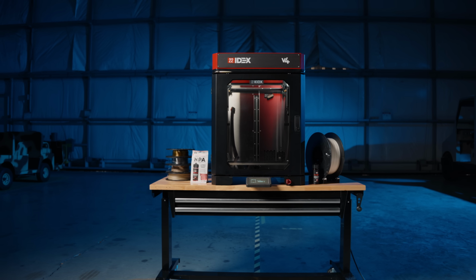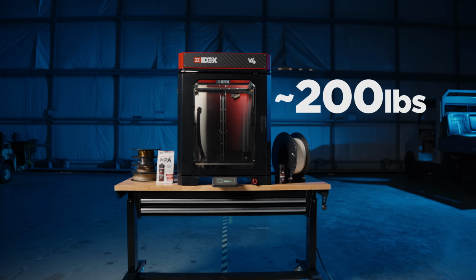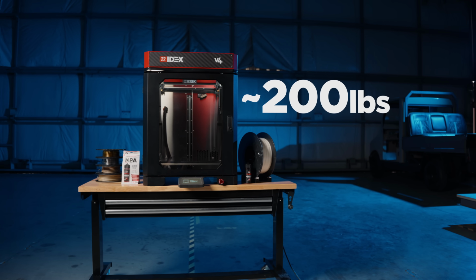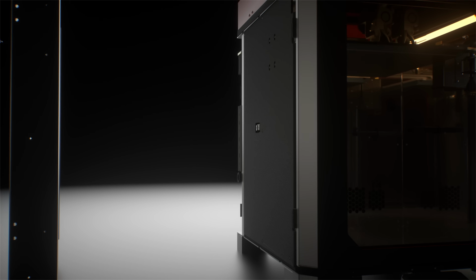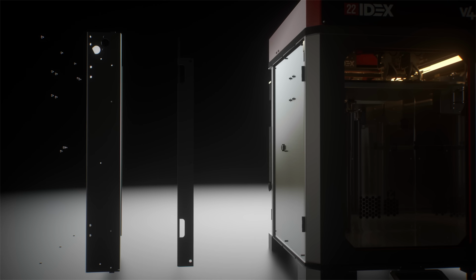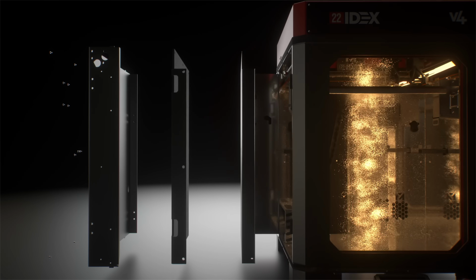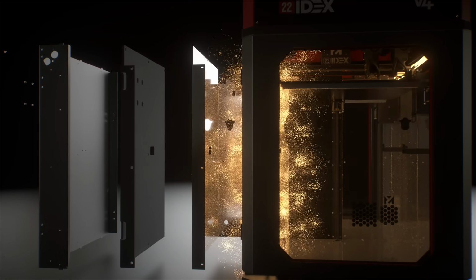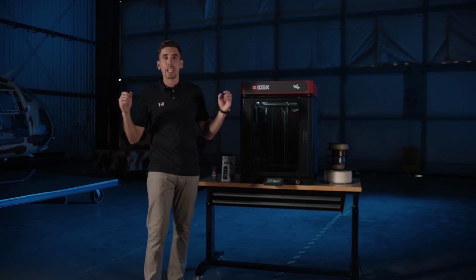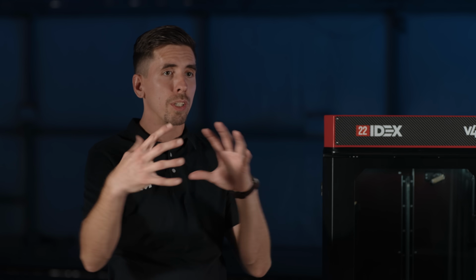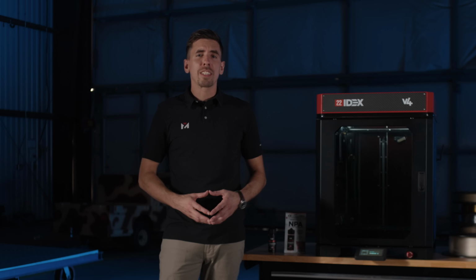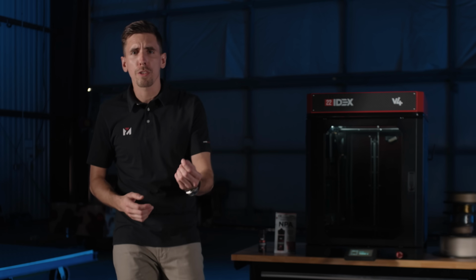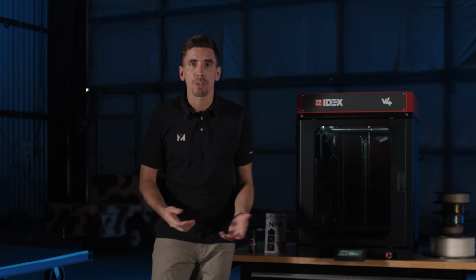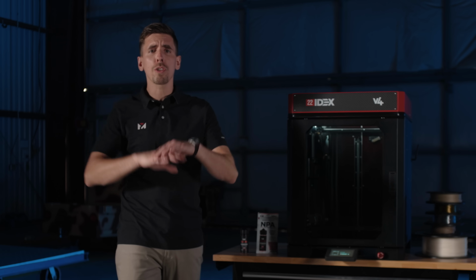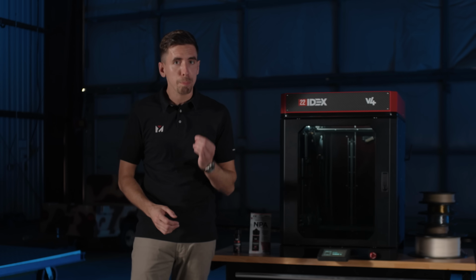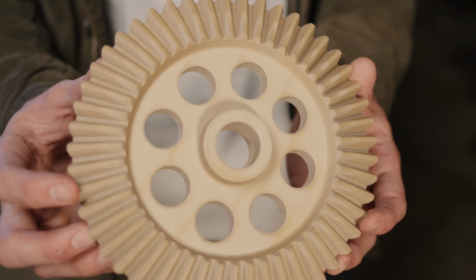This machine is almost 200 pounds. It's rock solid welded steel. On the outside is a powder-coated heavy steel frame. Inside of that, foam insulation, and inside that, the stainless steel interior. Now this stainless reflects the infrared heat from around the chamber and back into your part. This gets you faster heat up times, better thermal consistency, lower energy use, more efficient energy use, and overall better part quality, especially on the high temp, high warp materials.